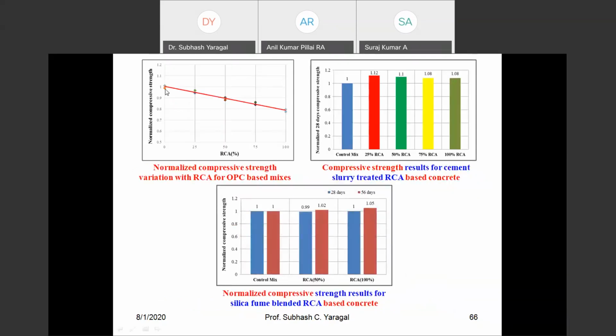So what we have done: if there is no replacement, 100% virgin, you have the strength here. We have written normalized compressive strength. We go for 25% replacement of virgin coarse aggregate by recycled coarse aggregate, you lose strength. If you do 50%, further loss, and if everything is recycled coarse aggregate, you usually lose about 20 to 25% strength in concrete. Now, what we have done in this effort is I am reporting the compressive strength results for cement slurry treated RCA. So we have taken around 5% cement slurry, and the recycled aggregates are kept immersed in this cement slurry for 1 day. They are sun dried and they have been used in making concrete.